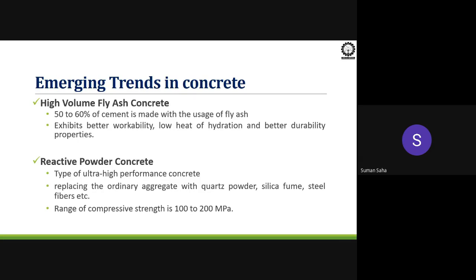To make it super compacted and gain high strength, usually quartz powder and silica fume are used. Even fly ash and GGBS are also used. As we incorporate these materials, we try to reduce the coarse aggregate. I think a very minimum quantity of coarse aggregate is there in reactive powder concrete. It's now an emerging area for research, or to apply in our daily life, but it has a lot of drawbacks. We have to work on that and make it usable effectively.